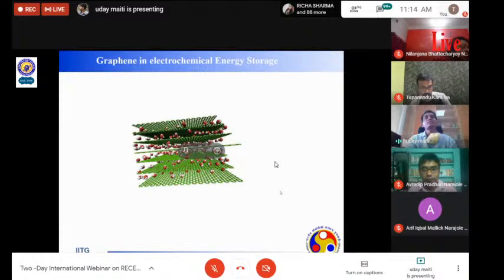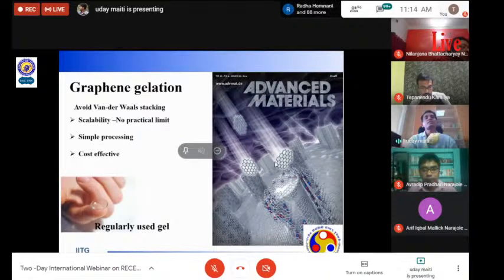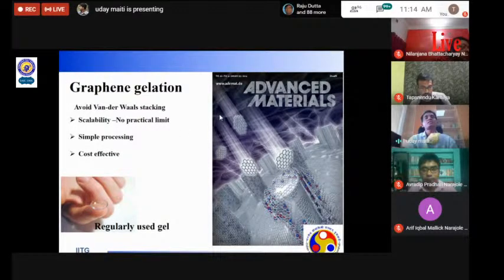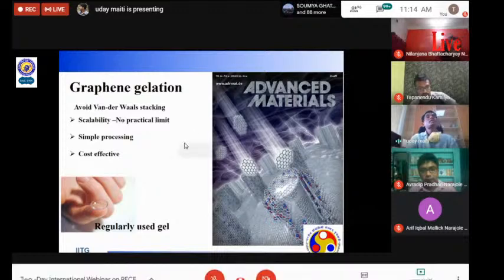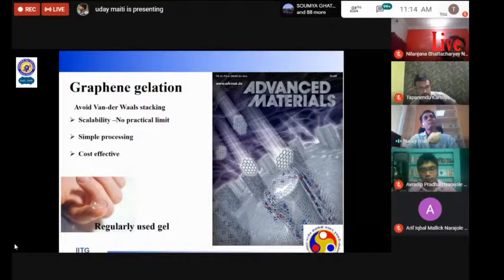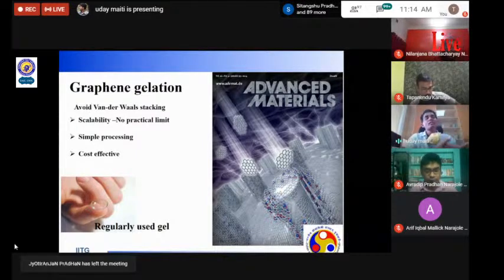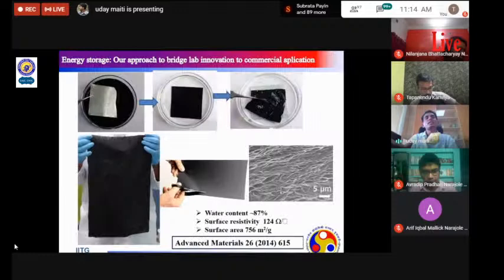There are different strategies. I have adopted a strategy which is known as graphene gelation. I started with some micron-sized sheets of graphene dispersed in water, and by some simple methodology, I made them assemble on the interface. When they assemble on the metal interface, the water remains intercalated between the graphene sheets, so that I can reduce the restacking of the graphenes. This particular material is very similar to a gel. You know that the contact lens is also a kind of gel. So a similar kind of gel we have prepared from graphene.